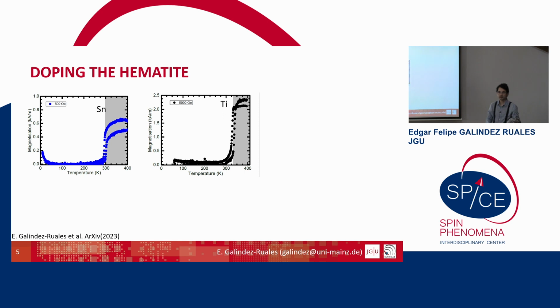When you go from the bulk value of 260 Kelvin to thin films, around 100 nanometers, you reduce this value to 200, and if you keep going down with the thickness of the sample, this temperature can go really, really low. Up to, I don't know, 50 Kelvin is the lowest Morin temperature that we are measuring, in samples of like 20, 25 nanometers. But then when you dope the hematite, you increase the Morin transition.